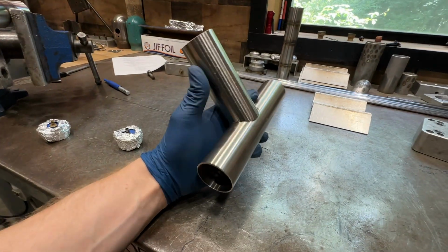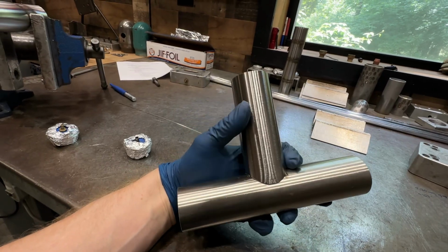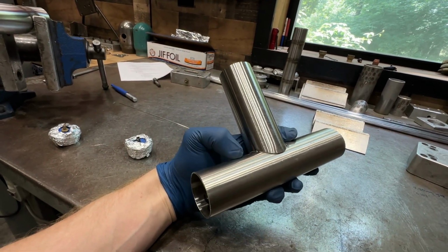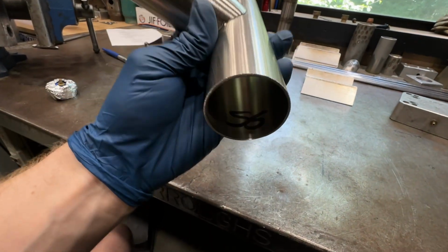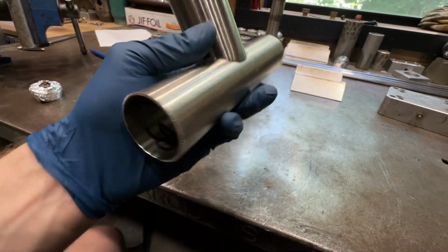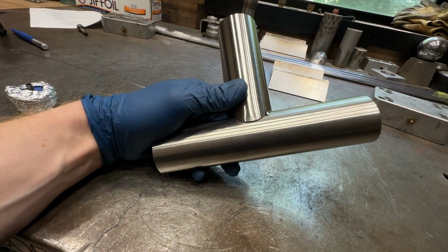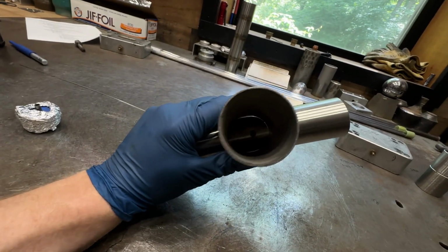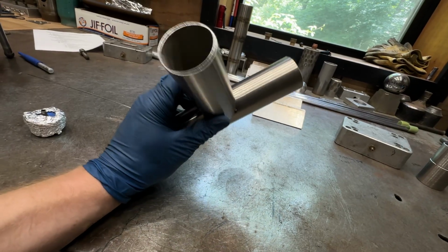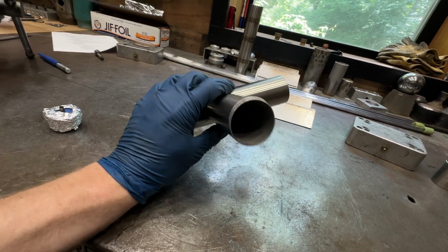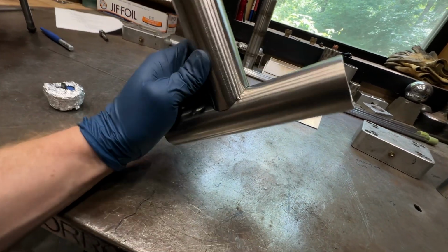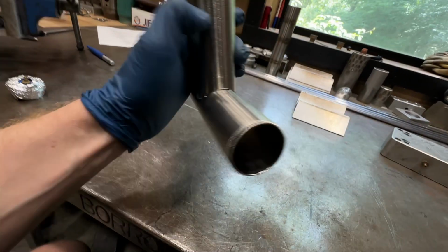And although this joint is not the same as that, it still serves as the proof of concept to show that you can weld this nickel alloy to stainless. So on the bottom, you can see I labeled it SS for stainless. It's just a piece of 304 stainless tube. And I just drilled a simple weep hole into the stainless tube, and I'll purge this and everything will be cool. So I have 4 tacks on it currently.